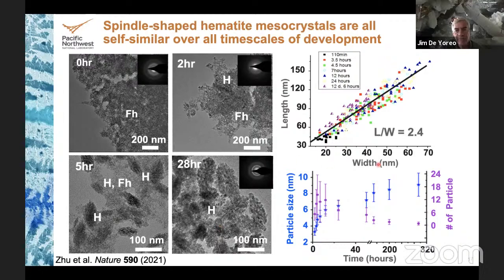And if you look at the length versus width for spindles of various sizes at various time points, you find that this aspect ratio is always the same. The particle sizes within the spindles all follow the same curve. The number of particles in a spindle all follow a certain curve. And so you have to ask yourself, how do you get a deterministic process out of a random nucleation diffusion process? And you would say, well, it can't be that.